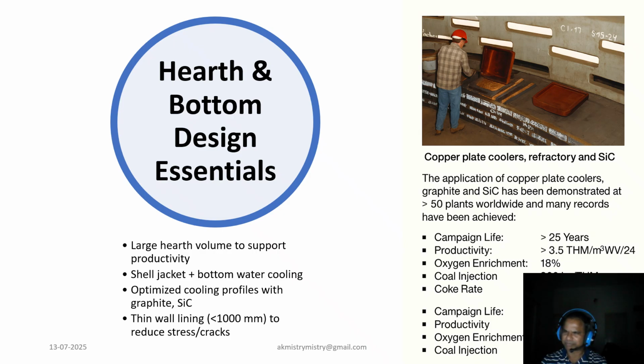So we can say that productivity begins at the base. A large hearth volume supports throughput, while shell jacket and water cooled bottoms regulate temperature extremes. Now, using graphite and silicon carbide in cooling profiles fortifies against thermal shock very nicely. Thin wall lining under 1000 millimeters helps contain stress and prevent crack propagation. And this leads to extending the campaign life from the very foundation.